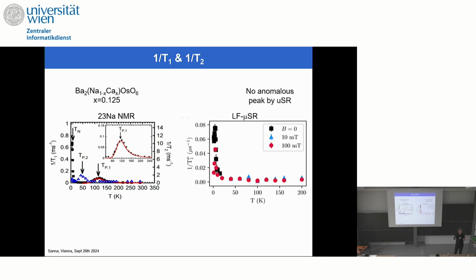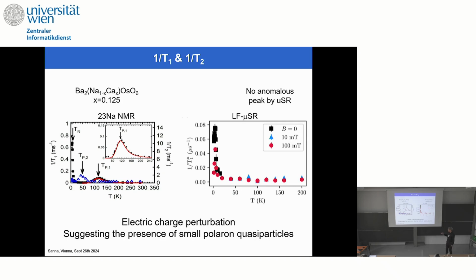which cannot be of magnetic origin, probably, because magnetic ordering is at a very much lower temperature. And we have the proof of that by µSR, which is sensitive mainly to magnetic coupling, and we don't have any relaxation peak in the µSR results, only the peak at the magnetic transition, as it should be. So it means that these extra peaks are related to a charge dynamical phenomenon, which means that we have electric fluctuating charge perturbation, suggesting the presence of small polaron quasi-particles.